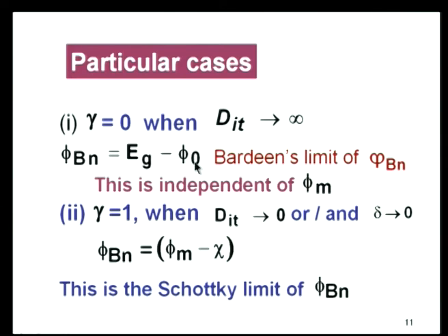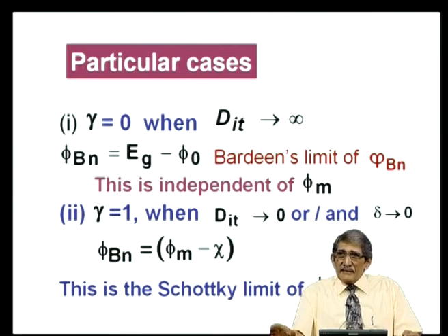So, what is the result of that? In silicon, phi_0 is 1/3, phi_0 is E_g by 3. So, what will be the phi_bn in silicon? For most of the semiconductors, it will be E_g minus E_g by 3, that is 2/3 of E_g. So, 1.1 is the band gap, and you will have a barrier height of 0.7 electron volts. It will always be rectifying, because the barrier is high. If the barrier height is low, you would have got ohmic contact.